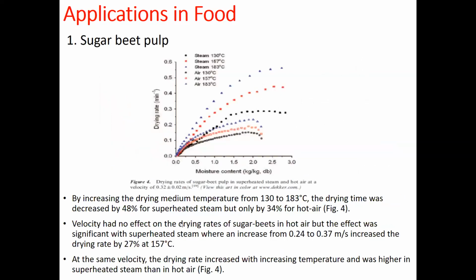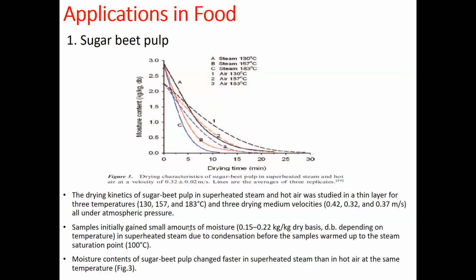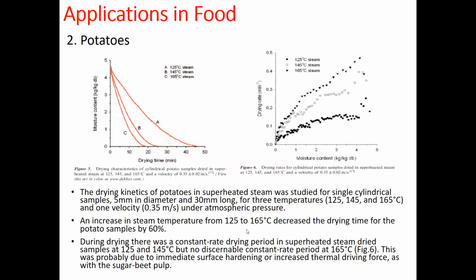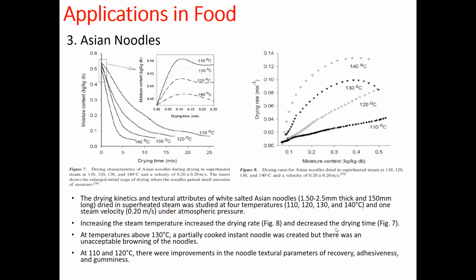Under atmospheric pressure, increasing the temperature of the steam increases the drying rate, and it can decrease the drying time. At temperatures above 130 degrees C, a partially cooked instant noodle was created, but there was an unacceptable browning of the noodles. So above 130 degrees C is not recommended for the noodles because of the browning effect. But at 110 and 120, there was improvement in the noodle textural parameters, where the adhesiveness and the gumminess were much preferred by the consumer.